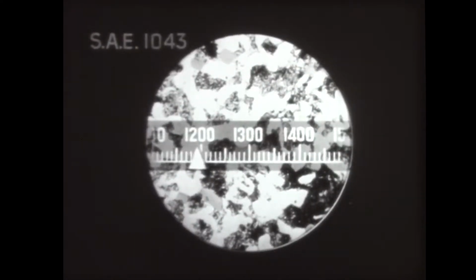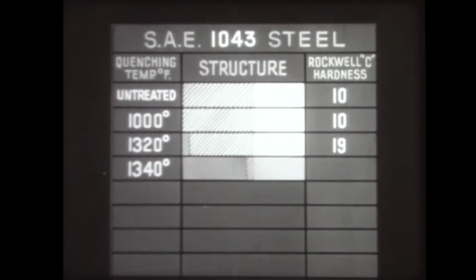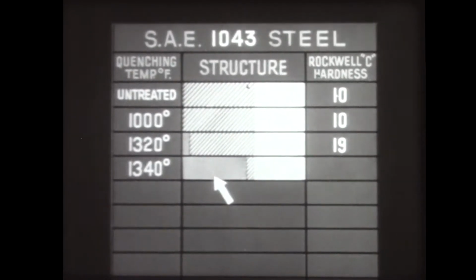Now let's heat the steel to 1,340 degrees. When quenched from this temperature, most of the pearlite changes to martensite. The original ferrite is still present. So the martensite area has increased. The additional martensite accounts for a rise in the steel's hardness, which is now 27.